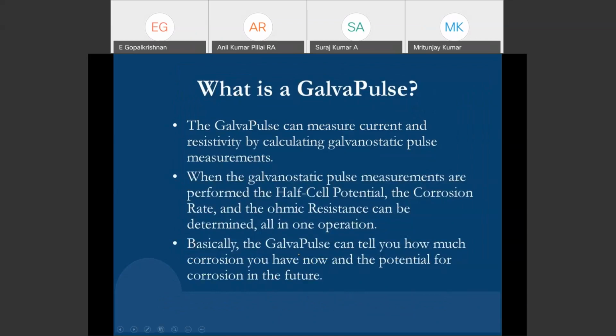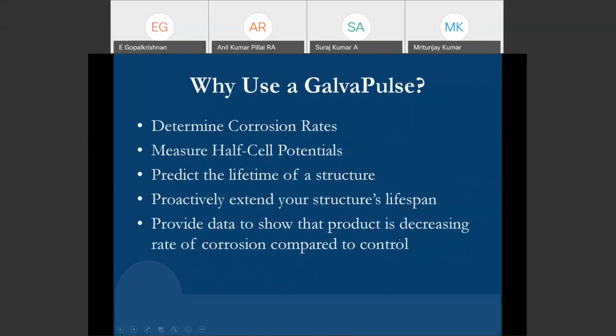As I said, these three pieces of information, the half-cell potential, corrosion rate, and ohmic resistance, are determined in one single operation; you can get all three. Basically, the GalvaPulse can tell you how much corrosion you have now and the potential for corrosion in the future. It measures the corrosion rate and half-cell potential. Based on that, we can predict the lifetime of the structure. We call it the residual life of the structure. We can proactively extend your service lifespan when you protect it from corrosion. Okay.